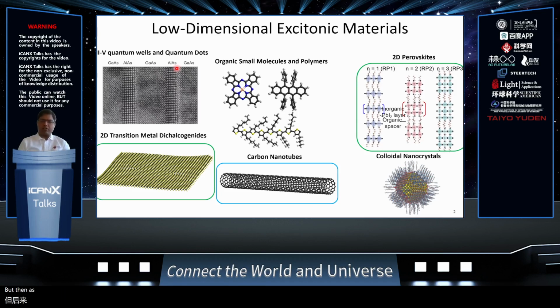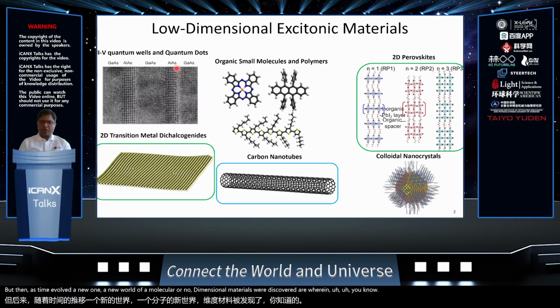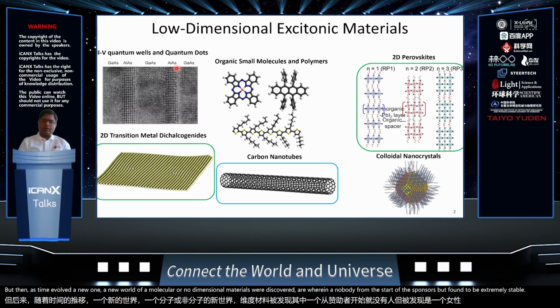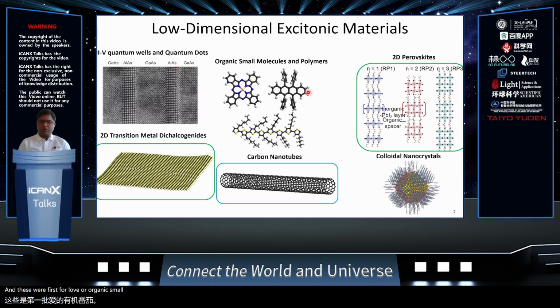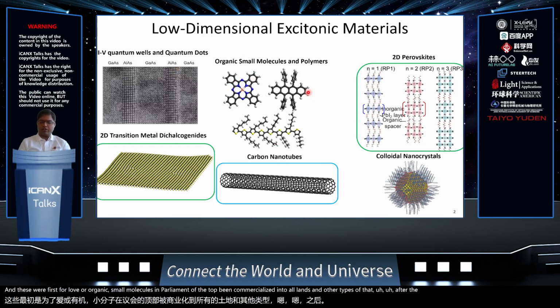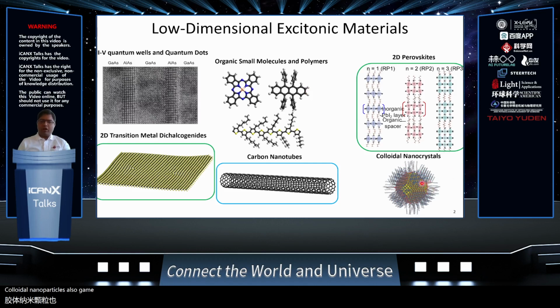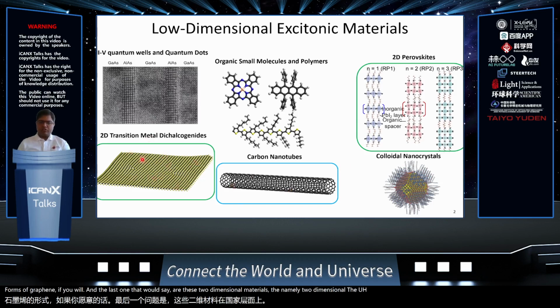But as time evolved, newer and newer molecular or low-dimensional materials were discovered, wherein very strong excitonic responses were found to be extremely stable at room temperature. These were, first of all, organic small molecules and polymers, which have been commercialized into OLEDs and other types of optoelectronic devices. Colloidal nanocrystals also came along, and then carbon nanotubes, which are one-dimensional forms of graphene, if you will. And the last ones, I would say, are these two-dimensional materials, namely two-dimensional transition metal chalcogenides and also some halide perovskites.